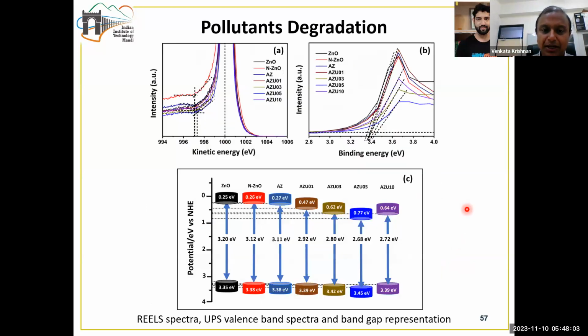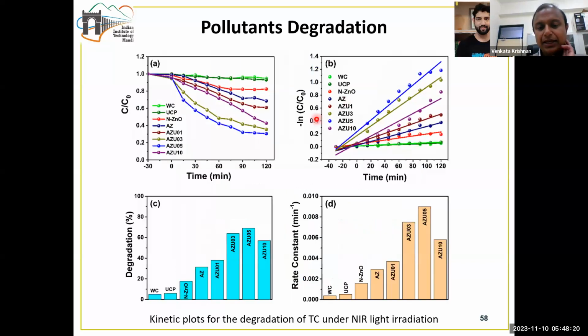Then we did the REELS and the UPS spectra in order to understand what the band gap is. Experimentally, we can determine the band gap, especially the valence band edge position. We were able to experimentally determine that, and then we were able to figure out what is the band gap of this material. Then once we did all these characterizations, we utilized this for the photocatalytic degradation of